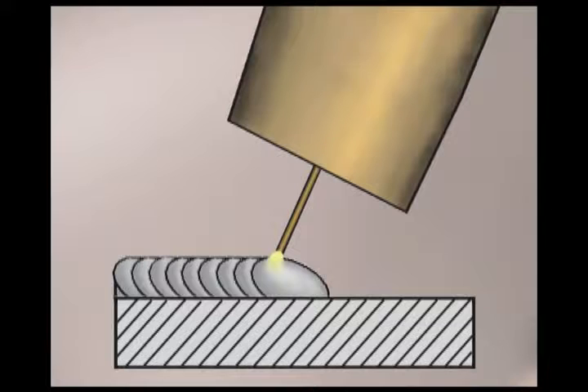If the wire is directed at the back of the puddle, with molten metal floating in front of the arc, the weld buildup keeps taking the heat, not allowing the base metal to get hot enough to melt. The weld can actually float right on top without penetrating or fusing to the base metal. This is a common problem, a great looking weld that does not hold the metal together. For good weld fusion, maintain the short wire stickout and stay ahead of the weld, keeping the wire on the leading edge of the puddle.